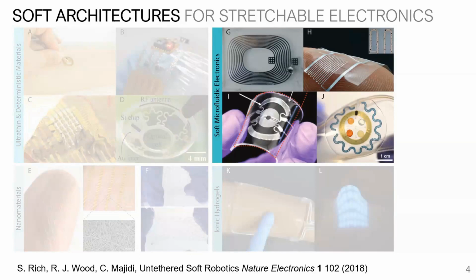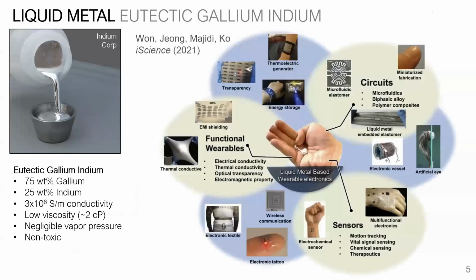I'll start by talking about some of what we've discovered with liquid metal, which is a particularly versatile material for this. We use a eutectic blend of gallium and indium, two metals that are solid at room temperature, but when you mix these together, you form a eutectic that's liquid. Depending on the size of the liquid metal, in the form of microfluidic channels or microscopic or nanoscopic droplets, you can get this alloy to remain liquid even down to very low temperatures, as low as -70, -80 degrees C.